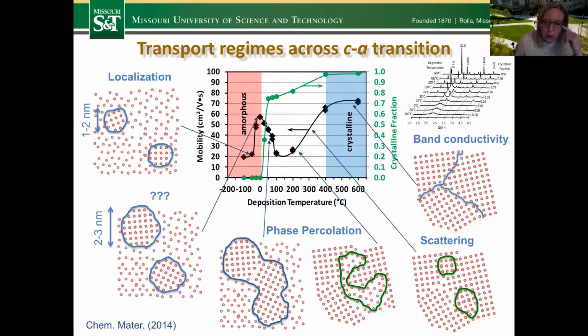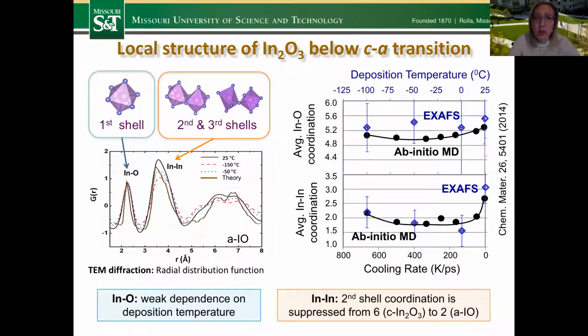It reduces, of course, because we start to develop an amorphous phase that grows, so we have phase percolation, and then the mobility increases back up just at the onset of the transition to truly X-ray amorphous material, and then drops back, which can be explained by strong localization. But of course, the question is what happens here, how we can explain this peak, because again, just the nanostructure, the size or the density of those nanocrystallites alone, they cannot explain the mobility peak. So first we have to start from the structure, looking at the local structure of indium oxide below the crystalline to amorphous transition. First, just the general radial distribution function.